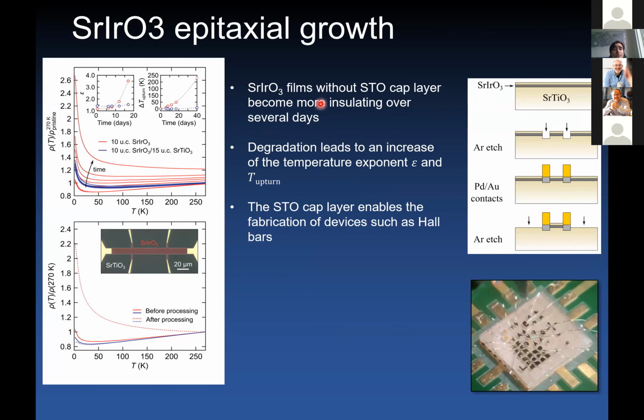I was telling you that we always cap our films with strontium titanate, and this is very important if you want to perform systematic studies as a function of thickness of these systems, because these films tend to degrade dramatically when exposed to ambient conditions. The strontium iridate films, if you leave them in ambient conditions over time, will turn insulating, and you will see that a lot of chemistry is going on at the surface with interaction of your films with the humidity in the environment. If you instead cap your system with an epitaxial strontium titanate, your system is stable over time and can be processed in the clean room to realize transport devices. So we systematically study different thicknesses, and we are able to fabricate Hall bar devices.